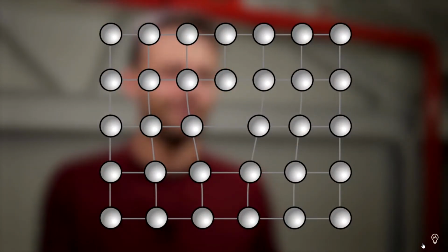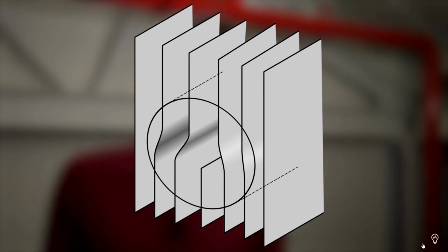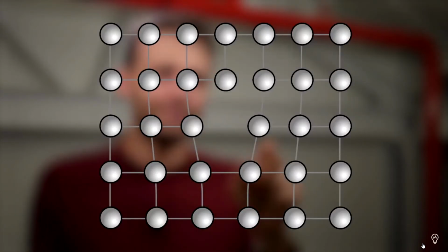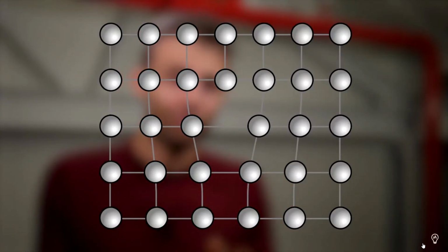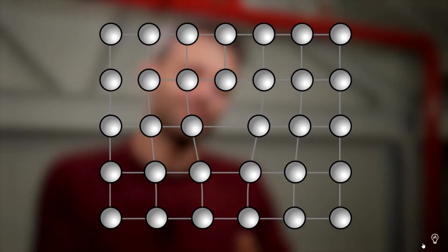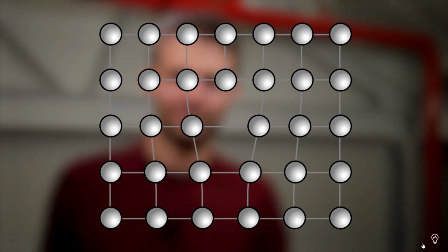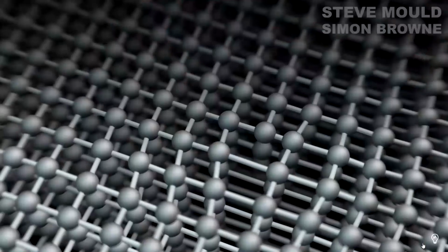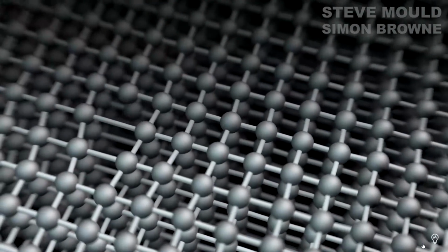And it turns out that dislocations are easy to move. You can see why. If you look at the bonds around a dislocation, they're already quite strained, so you don't need much energy to break one of those bonds. So when you apply forces to a metal in different directions, these dislocations will move around in different directions, like this. The important thing is it takes less energy to move dislocations through a grain than it does to move grains against each other. That's why dislocations are sometimes called the carrier of plasticity in a metal.